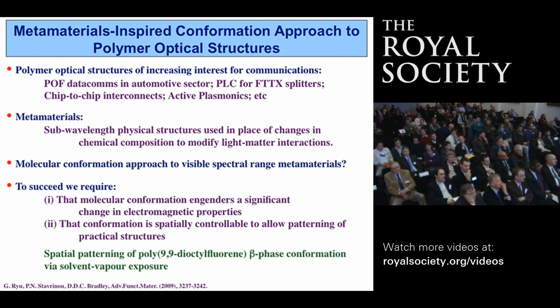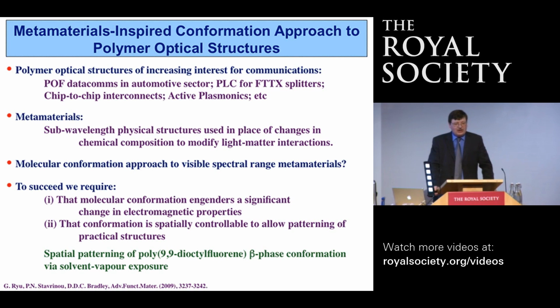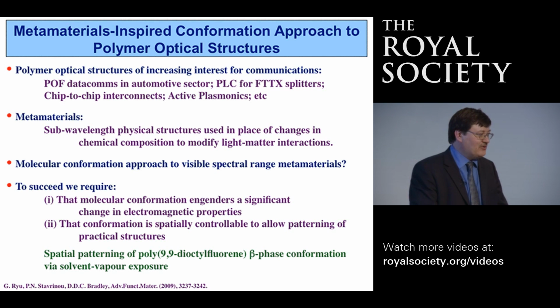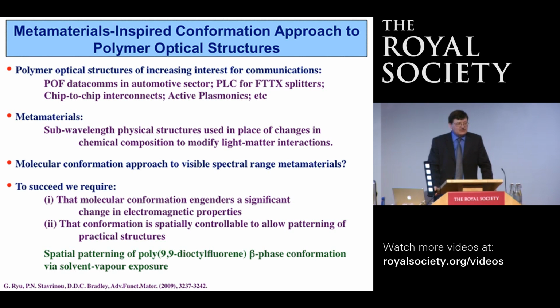Metamaterials are materials where we basically physically structure the material on a scale which is short compared with the wavelength of the radiation, the wavelength of the light that we want to interact with that material. And by doing that, we then have an averaging of the response of the material associated with that structuring. And in particular, you can make structures which show unusual properties. And some of the unusual properties are perfect lenses, and we can make negative refractive index materials. And those are typically made using metals, which are structured. And there are a whole range of different geometries that are used to achieve that effect.